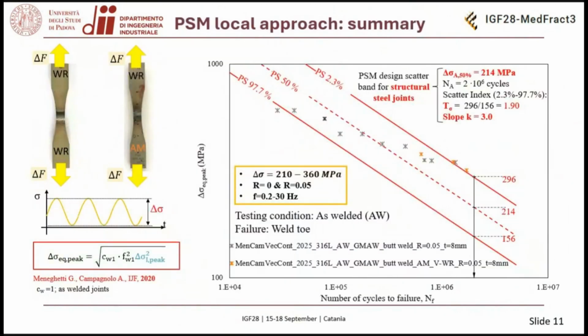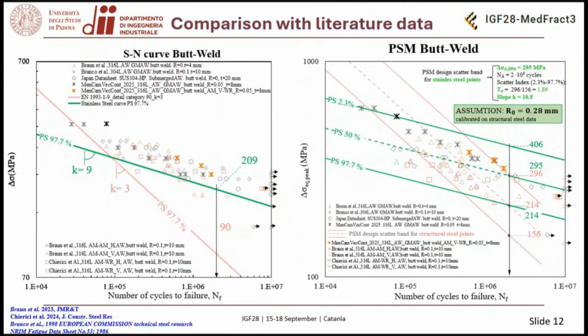All this data have been finally reanalyzed with the local approach, and here you can see them reported in terms of an equivalent peak stress. As said before, the data of additive welded joints are in good agreement with the traditionally manufactured ones. However, if compared with this scatter band, which has been defined for structural steel joints, they are not in good agreement in terms of the inverse slope. Then we also compare our data with the ones taken from literature, both in terms of the nominal stress and in terms of an equivalent peak stress. As you can see, they are in good agreement with the literature data.